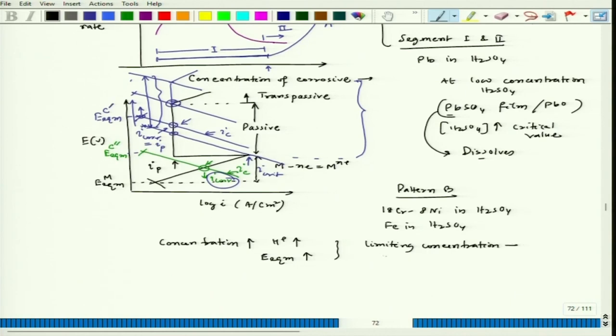limiting concentration, the ionization of acid decreases. Once ionization of the acid decreases because of the increase in concentration, hydrogen ion generation also decreases. So as hydrogen ion generation decreases, and with increase in further concentration, the ionization becomes very limited. So that's why at times, for example, iron, plain carbon steel, if we hold concentrated H2SO4, we get to see a very, very low corrosion rate of iron, because of the very situation that concentrated H2SO4 doesn't ionize much. And of course, it is at ambient temperature. It's not at high temperature, the room temperature or low temperature.